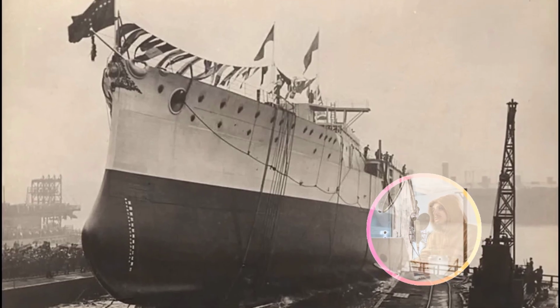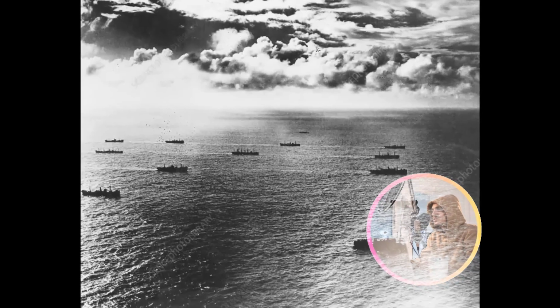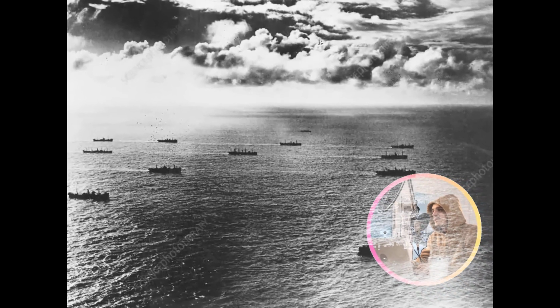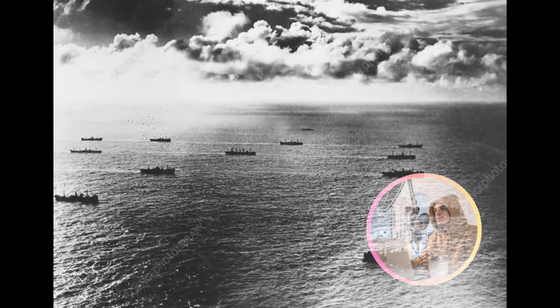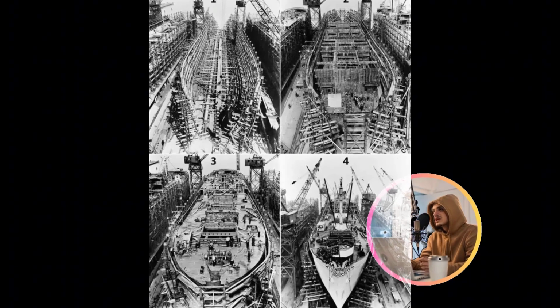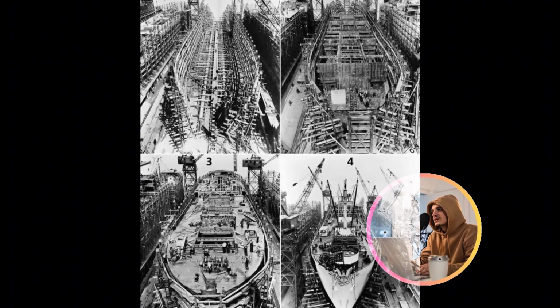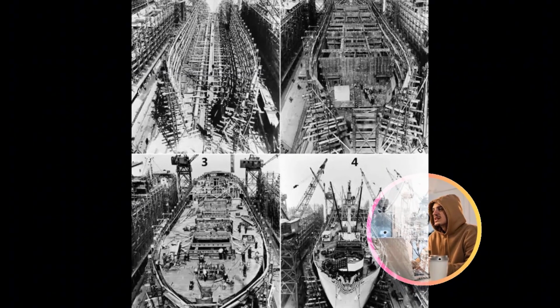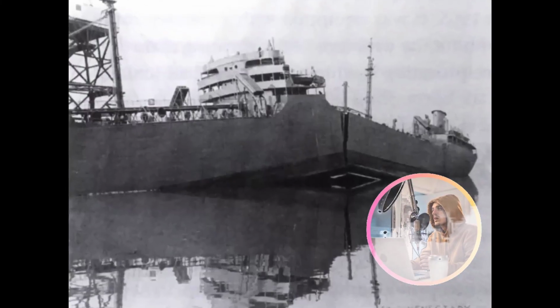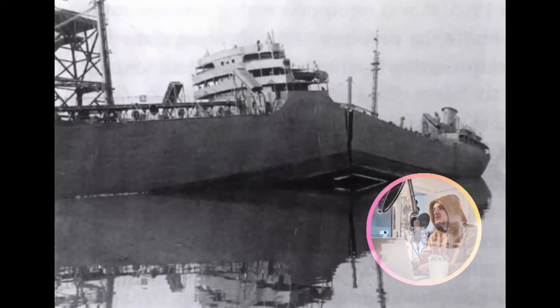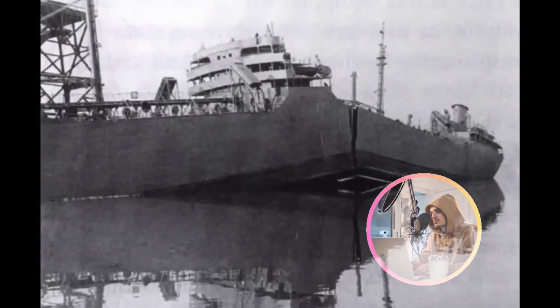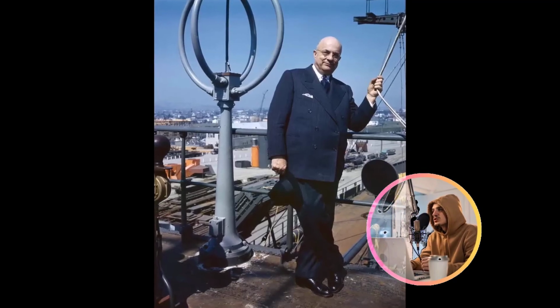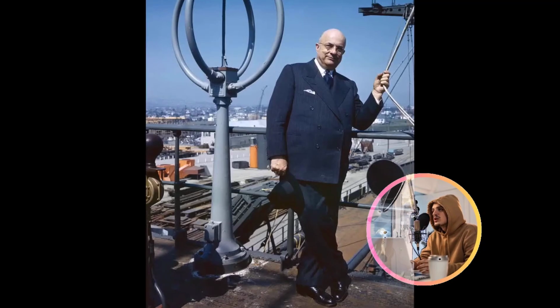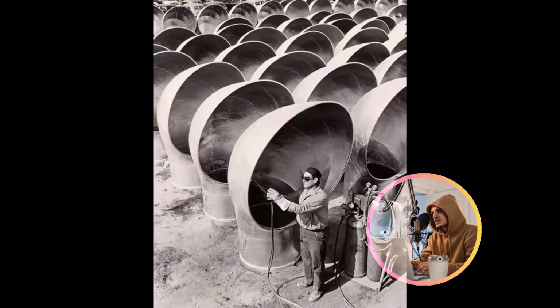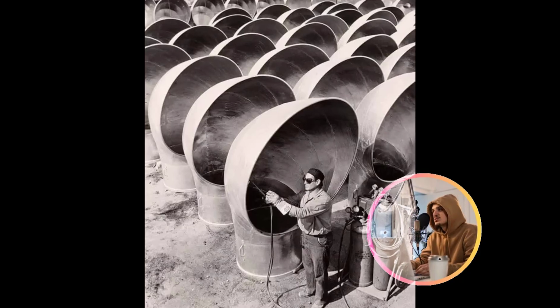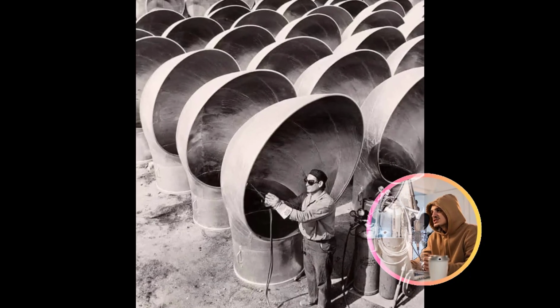Kaiser's dedicated engineers embarked on a systematic process, meticulously working backward from every identified point of structural failure. Consequently, every single rectilinear corner present in the original Liberty design was meticulously replaced with smoothly rounded transitions. The critical hatch openings, which had tragically served as the genesis for so many previous cracks, were comprehensively re-engineered with generously proportioned radii, thereby effectively nullifying the stress multipliers that had previously transformed routine operational loads into potent fracture initiators.